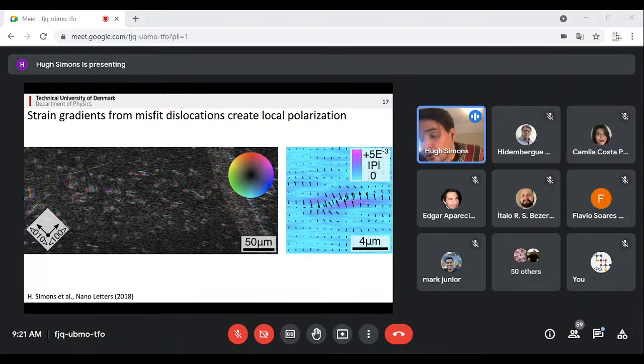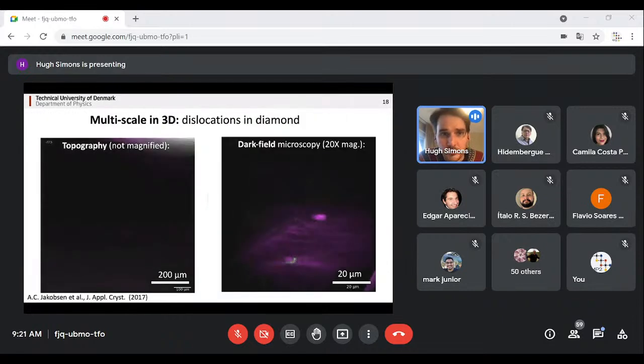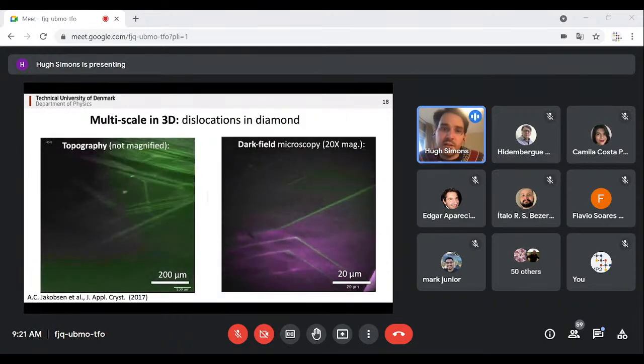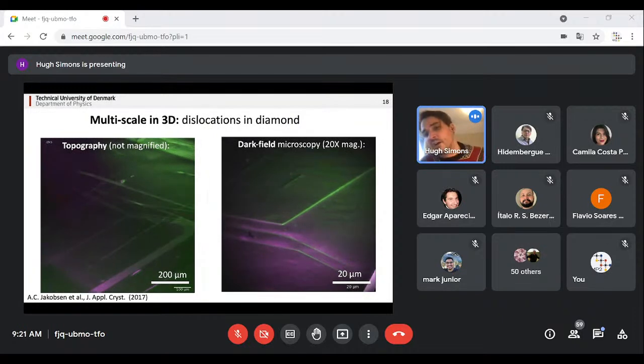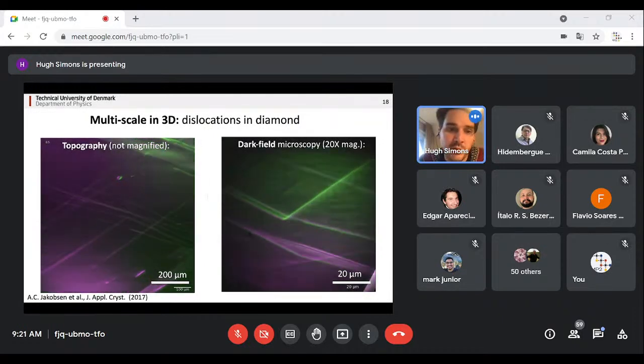And so from this, you learn that these misfit dislocations actually create stray electric fields, and therefore they should have an electrical impact on the properties of these materials. So we thought this was pretty interesting from the perspective of dislocations in thin films. But it was only in a thin sample. So soon after that, we started looking for some thicker samples with larger dislocations.